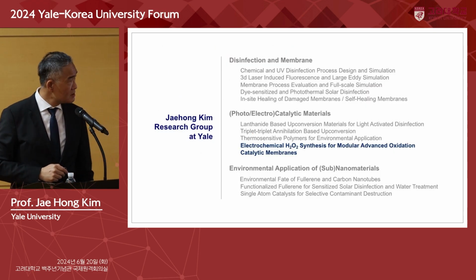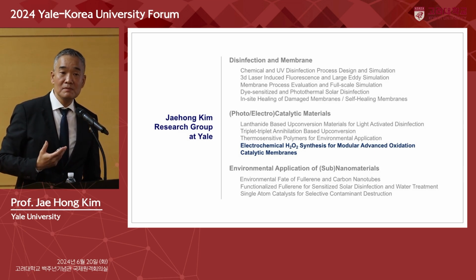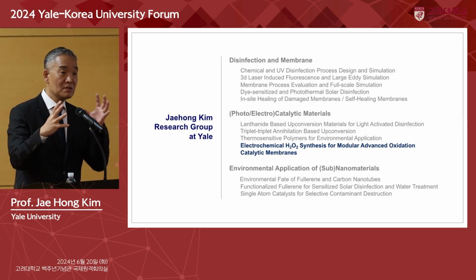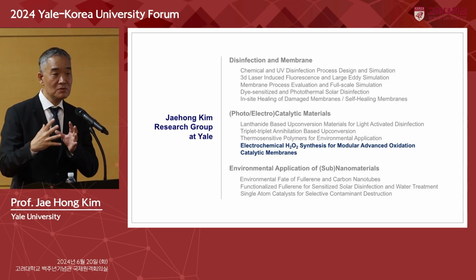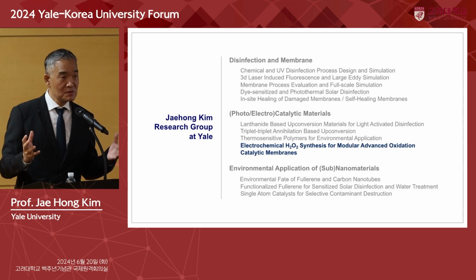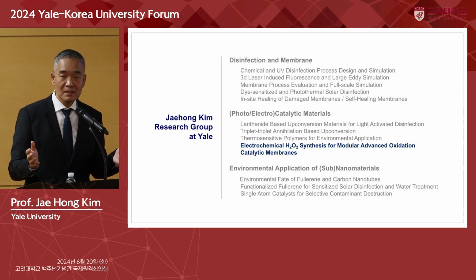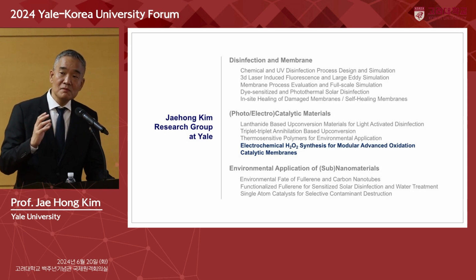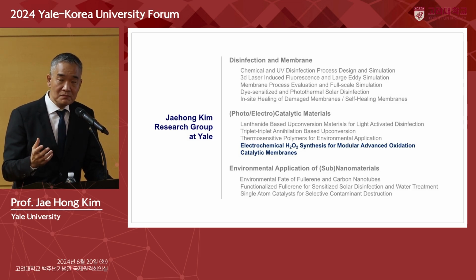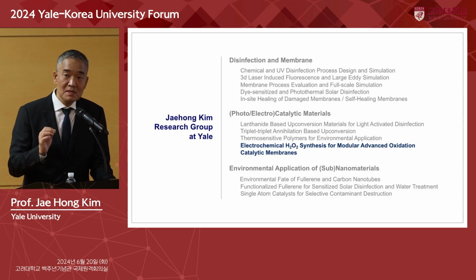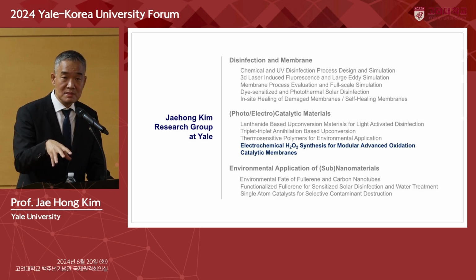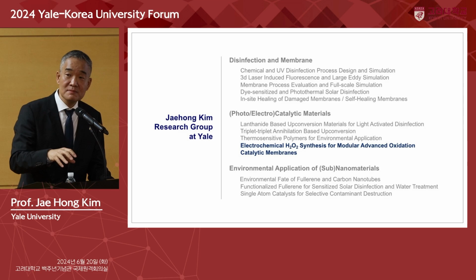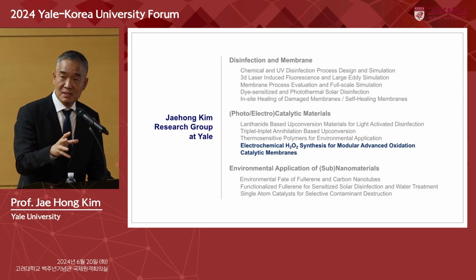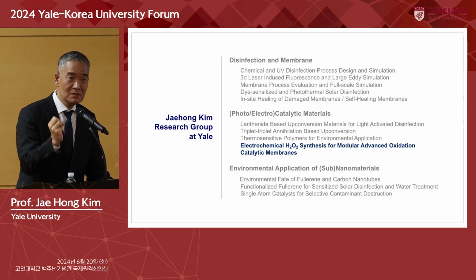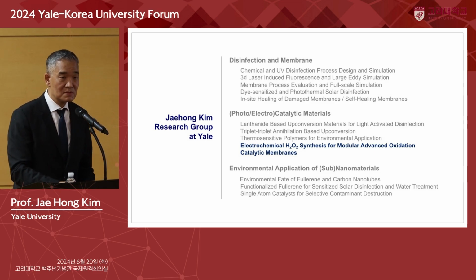Going to the next research, it is about advanced oxidation. In some physical separation, you remove the pollutant by concentrating pollutants, so you produce clean water, but you are left with a concentrated stream of pollutants, which is tougher to treat. So in many cases, when you are producing clean water, you want to destroy the pollutants, oxidatively or reductively. One of the oxidants that we use is the hydroxyl radical, which is an extremely reactive radical, but very short-lived. So what you have to do is start with a precursor like hydrogen peroxide, which is stable, and then you apply some energy, such as UV, to activate the peroxide and produce hydroxyl radical, and the hydroxyl radical goes and destroys the pollutant. That process is called advanced oxidation.